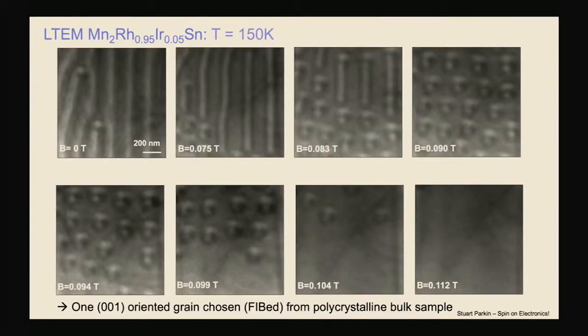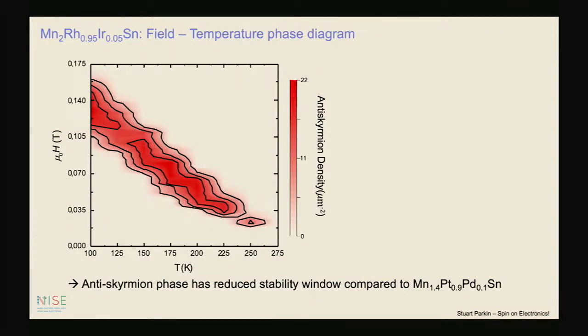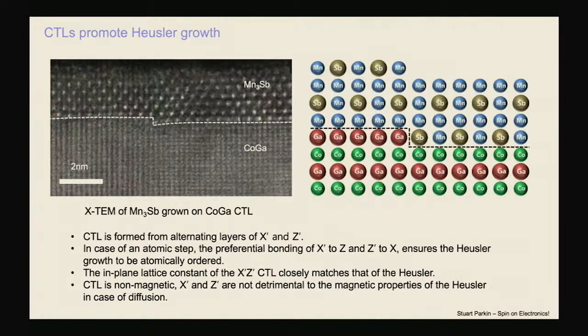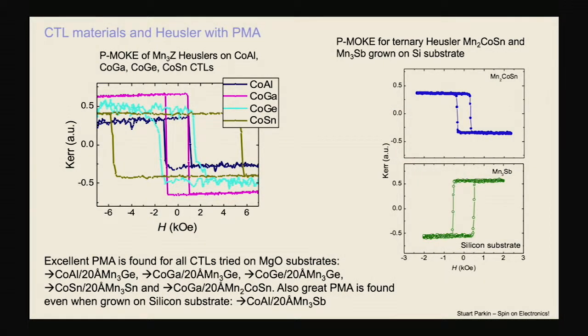So I don't have time to discuss that, and I don't have time to tell you that we've also seen anti-skyrmions in manganese rhodium tin over a more limited field and temperature range. And I won't tell you, we can now make thin films of these Heuslers, 1 and 2 unit cells thick, using a chemical templating technique that we recently published, and we're searching intensively for anti-skyrmions in thin layers, which we can then move using spin currents generated through spin Hall effects in heavy metals. We hope to see that shortly.